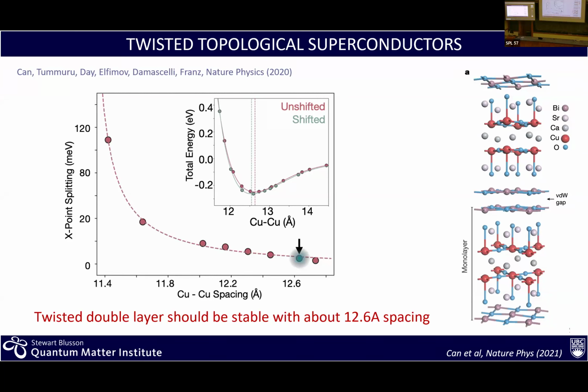Yes. So what breaks the time reversal symmetry in this setup? It is really the symmetry of the order parameter you are able to create. In this case, that does it. So you need that interaction between the two order parameters. Because when you stack two layers, the system has time reversal symmetry. So d plus i dxy comes out of spontaneous time reversal breaking. Right, yeah, because there are currents running now. What's missing is that the d-wave is plus, plus, minus, minus, so delta has a different sign. So you can twist to some extent, then plus may be somewhat above minus.